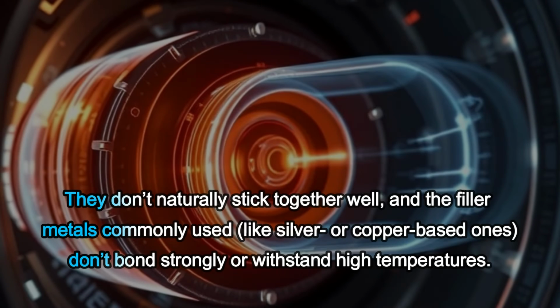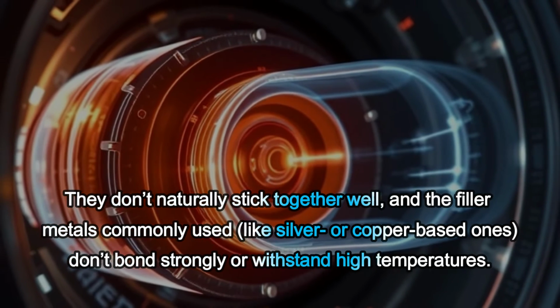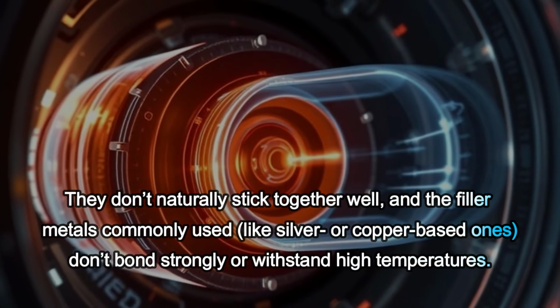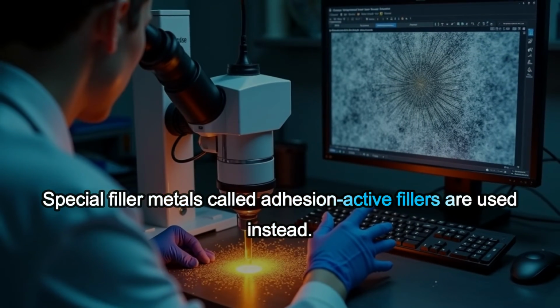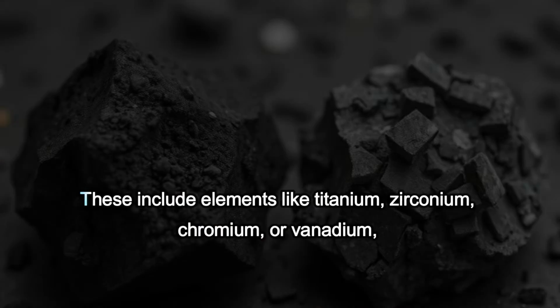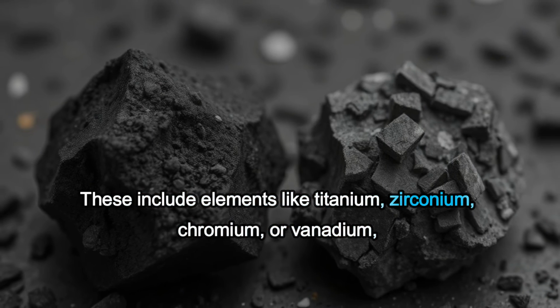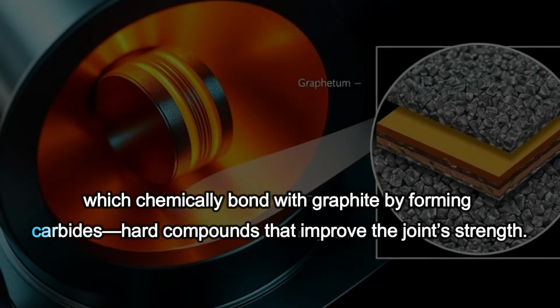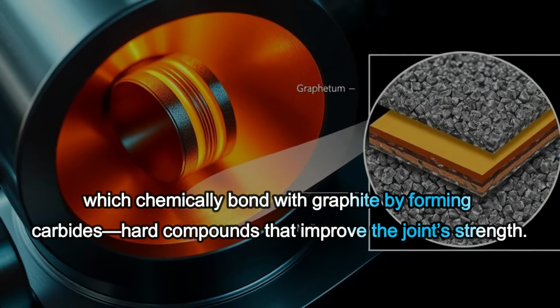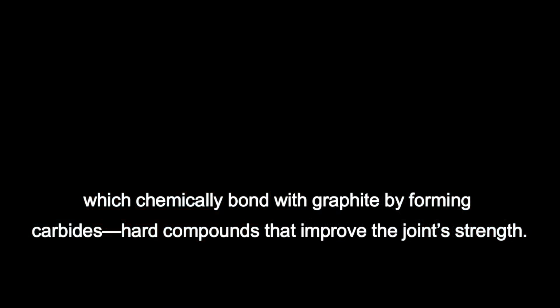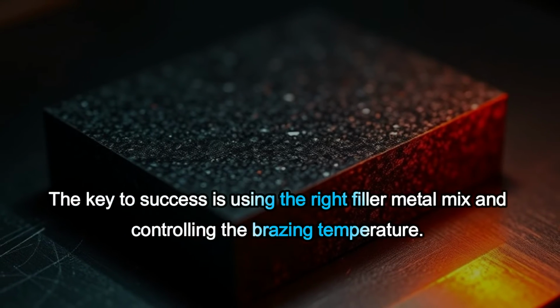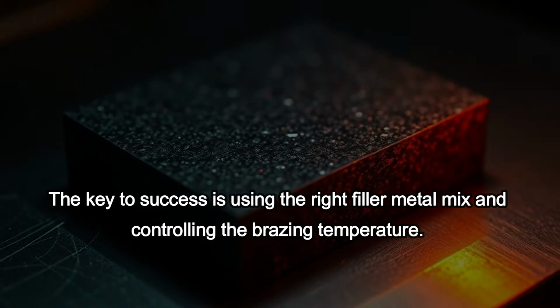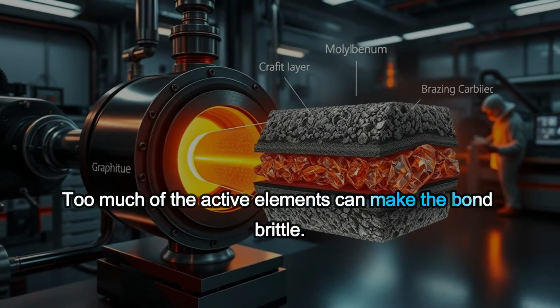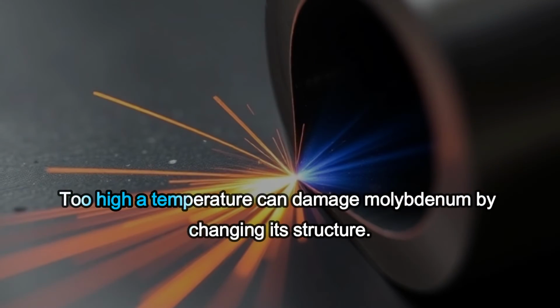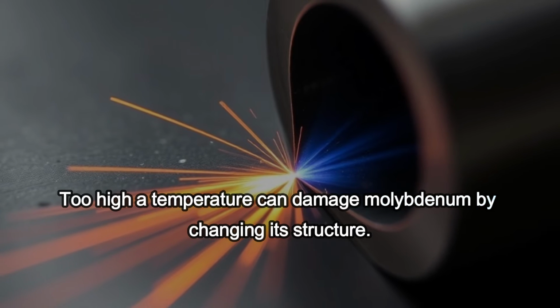They don't naturally stick together well, and the filler metals commonly used, like silver or copper-based ones, don't bond strongly or withstand high temperatures. Special filler metals called adhesion-active fillers are used instead. These include elements like titanium, zirconium, chromium, or vanadium, which chemically bond with graphite by forming carbides, hard compounds that improve the joint's strength. The key to success is using the right filler metal mix and controlling the brazing temperature. Too much of the active elements can make the bond brittle. Too high a temperature can damage molybdenum by changing its structure.